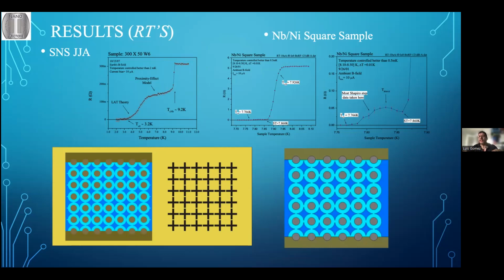So the way of fabricating this, Chris, is that first on the silicon wafer, we put the little coins, the ferromagnetic dots made of nickel. So we put those first, and then on top we deposit the film. And then finally, once we put the film, as clean as we can make the interface between one deposited on top of the other, then we'll do the lithography that will make the sample to be measured.